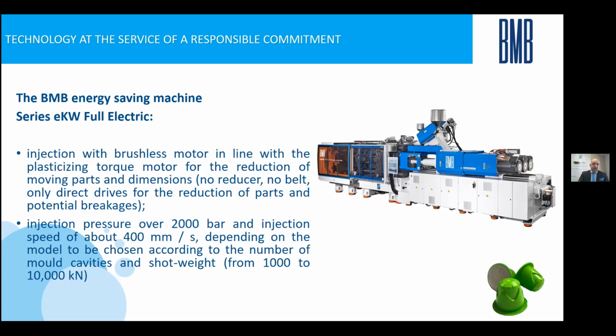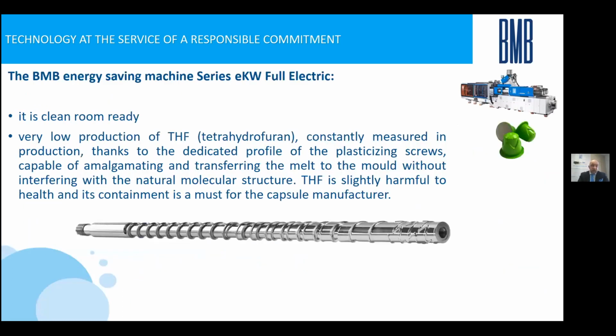Injection pressure for these capsules is very high, around 2000 bar, and the speed around 400 millimeters per second. Our range of the full electrical came from 100 ton to 1000 ton. The screw is very important in this type of transformation because this type of injection process try to produce THF, tetrahydrofuran. What is this? It is a not so good gas that will produce during the plasticizing moment if the treatment of the material is not so good.